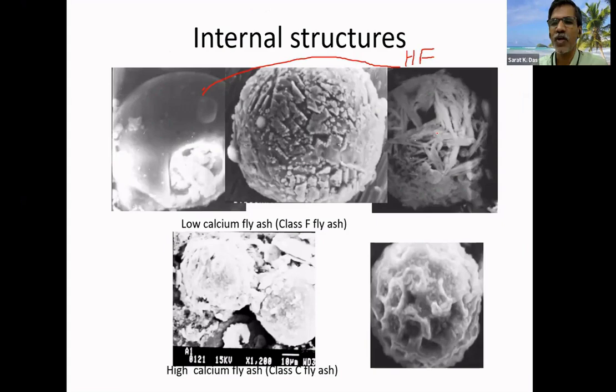And interestingly, others have found this type of structure in concrete where they have used fly ash as an admixture. So that means with time, this outer structure will go out and this type of internal structure will come out. And this is also identified and known as mullite. Mullite is another type of mineral which is rich in aluminosilicate. So these are the crystal structures, and this is the amorphous phase. So this is how the internal structure of a low calcium fly ash is.